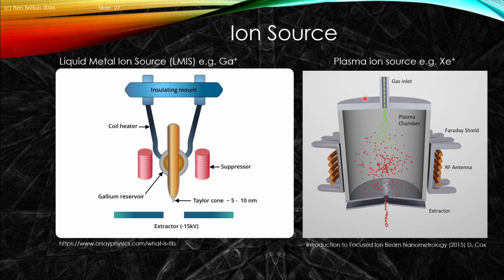We have the alternative source that enables us to form the so-called plasma. And one example that we use a lot at UBC is a xenon-based source. And in this case, we have an introduction effectively of a neutral gas. We're going to use a noble gas like xenon. It comes in, and then inside the plasma chamber, we're going to convert that neutral gas into effectively an ion cloud. And that ion cloud can then be pulled through an extractor hole. And that's done through effectively a chamber, the plasma chamber itself in this case.